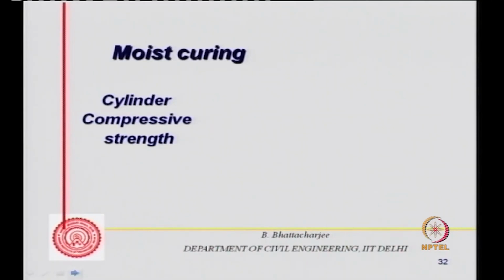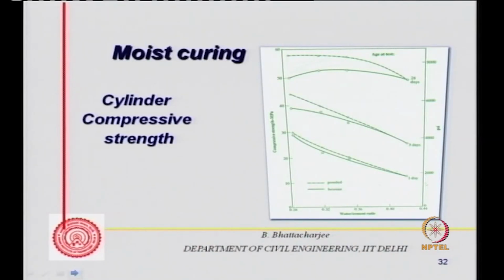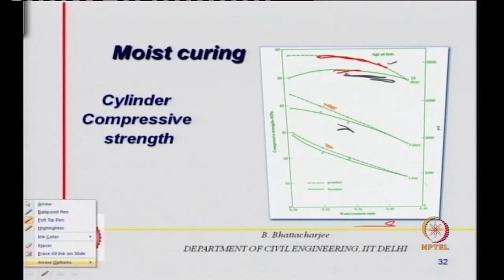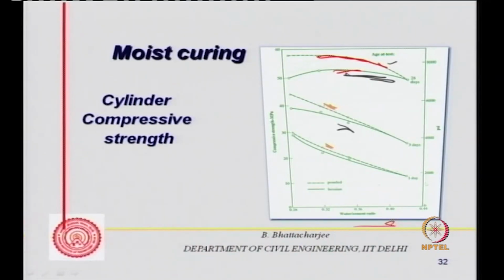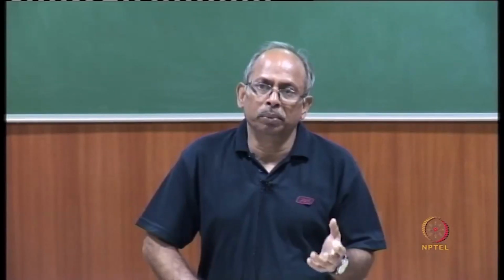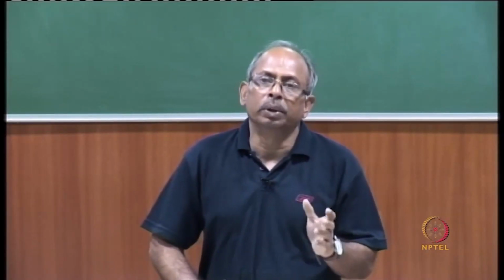Moist curing: if you see compressive strength, you can compare it. You see 28 days, and this side is for different water cement ratios. The comparison is ponded and Hessian. This high one is ponded, and Hessian cloth is somewhere here, lower. So ponding does a good job, actually a better job, and Hessian is relatively lower. This is for 1 day, this is for 3 days, this is for 28 days. So ponding does a better job than Hessian, or putting a water absorbing cloth or something covered.